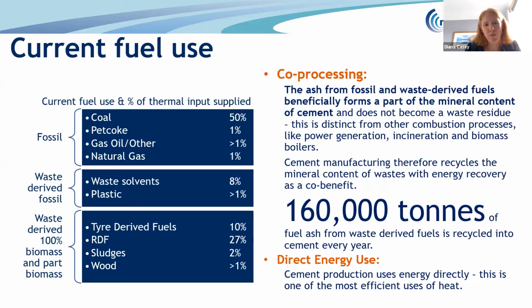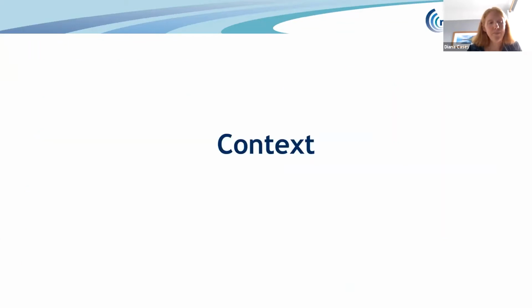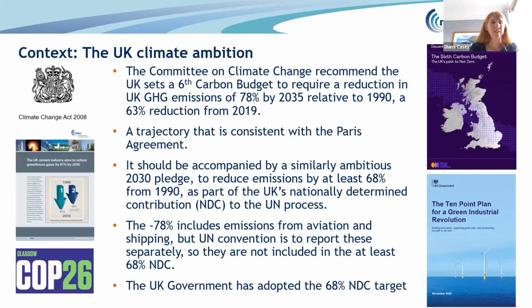It's also important when we start looking at fuel switching because the mineral content of the fuels reduces the raw material requirement, and changes in the fuel mix can impact the quality of that clinker because the ash is remaining in the product. Each year, around 160,000 tonnes of fuel ash is recycled into cement. So that's a bit of background to MPA and cement manufacture.